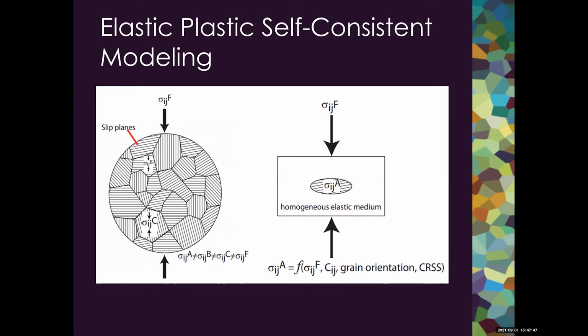Lal touched on this earlier, but just to reiterate, these models look at each crystal's role in a polycrystal as an inclusion in a homogeneous elastic medium. And as each crystal is loaded by the medium and deformed, the model then uses Eshelby's solution for an elliptical inclusion to solve for the strain, which is compatible for the crystal in the matrix. And since the elastic medium is an average of all the grains in the material, this has to be calculated iteratively. So as each crystal is loaded, this information is averaged back into the homogeneous elastic medium. And so this allows us to have different stress states for different crystals, depending on how they're oriented in their elasticity and plasticity.